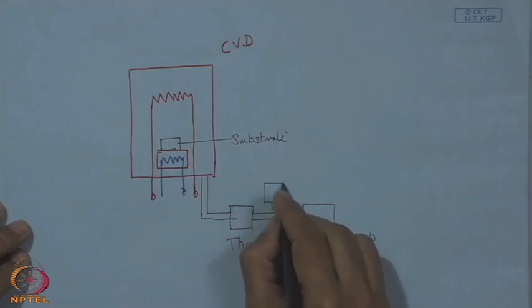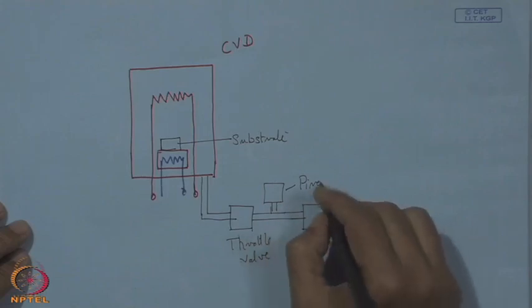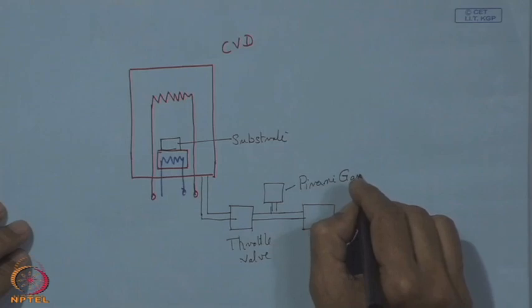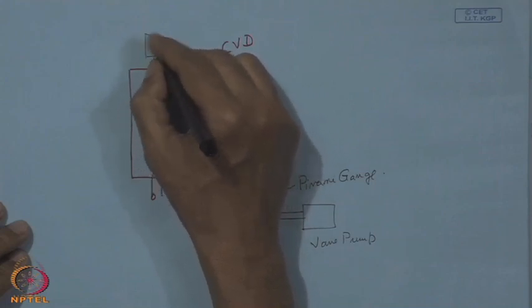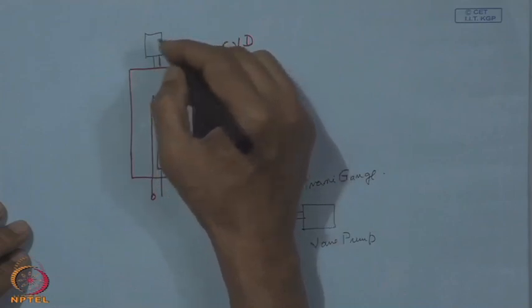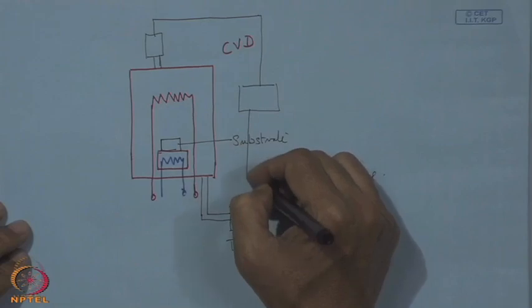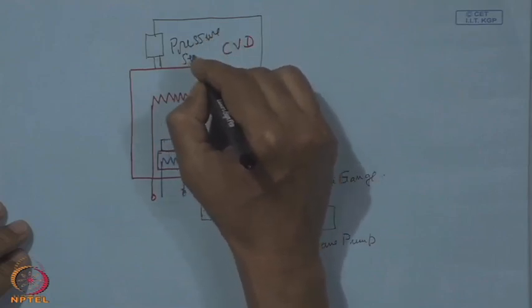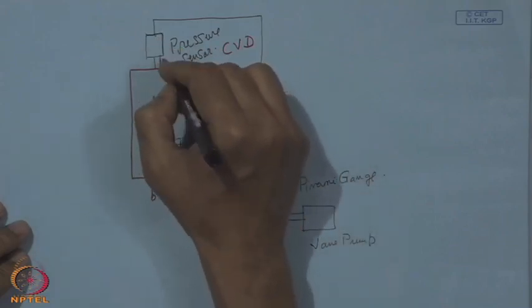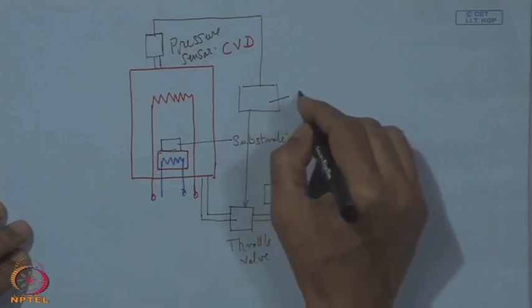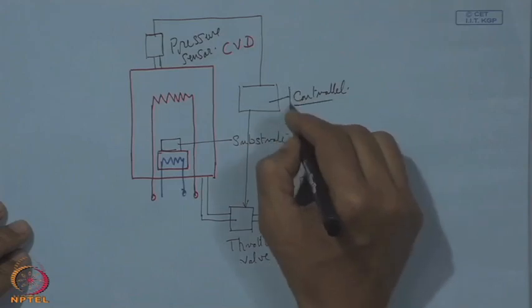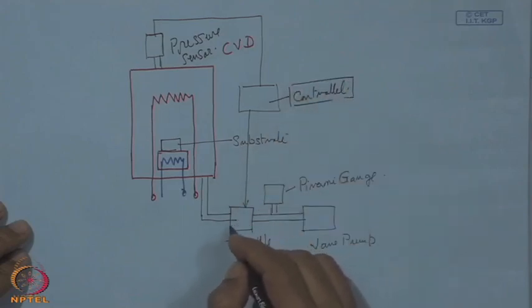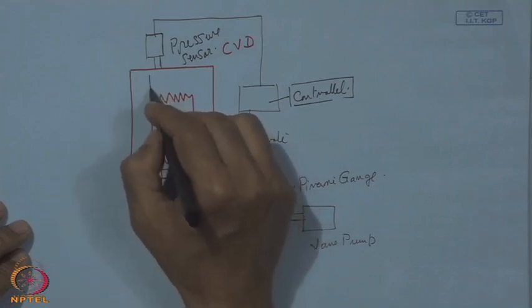Here we do have one Pirani gauge for measuring the vacuum. Now, this is the downstream side, and here at the top we can have a pressure sensor which can measure, monitor and regulate the pressure, and this can be through a controller, it can be coupled with this throttle valve. The basic idea here, this is the pressure sensor, it can be a capacitive pressure sensor. The basic idea here is that if we set a pressure value, then according to that requirement, this controller can regulate the opening of this throttle. It can be from 0 to 100 and it can set to a value to maintain a particular process pressure inside the chamber.